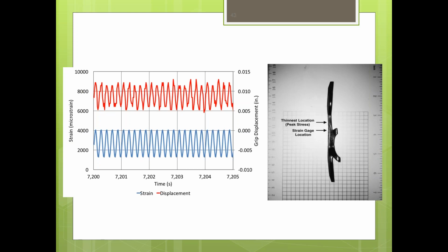On top of that live load real world application, Dr. Plummer did some additional research in the lab to really enhance and increase the amount of cycles that the plastics themselves are seeing. So they decided to punch out samples of the actual post-manufactured pipe, including, you can kind of see the valley and the corrugation meeting the liner there. And they placed the actual punched out samples from manufactured pipe from both recycled and virgin, and they tested in a lab condition where they are basically pulling on it with a significant amount more micro strain than you would typically see in a live loading application. If you noticed in the slide before, it was in the hundreds range, and the micro strains seen in these tests in the lab were in the thousands range, almost up to 10,000 in some of the peaks and amplitudes there.